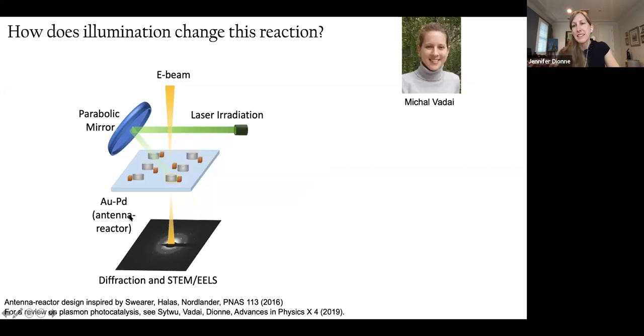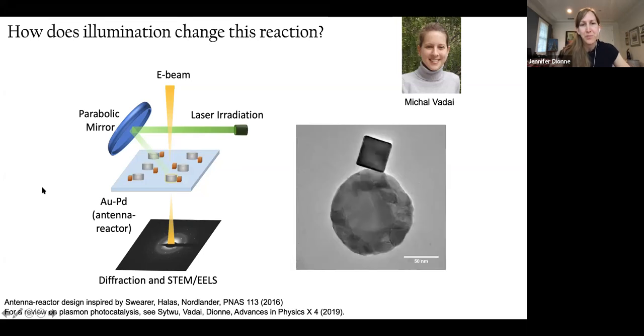And this is what brings me to light, and in particular, how we can use light not only to change the reaction kinetics, but also to change where the reaction is occurring. So we worked closely with Gatan, starting I think about 5 years ago, to develop methods to introduce light into and out of the environmental electron microscope. We essentially surround our sample with a parabolic mirror. The mirror has a slit through it to allow the electron beam to pass through, so that way we can also do tomography. And we designed the system to enable not only high optical incoupling efficiency, but also high optical outcoupling efficiency.